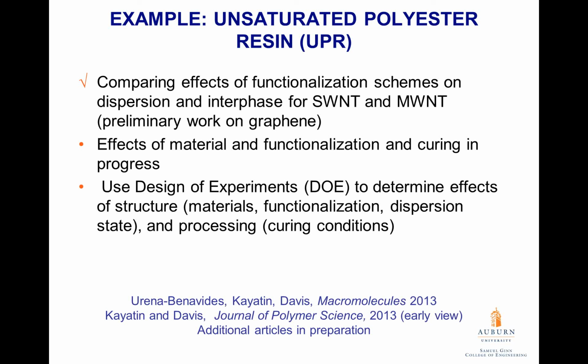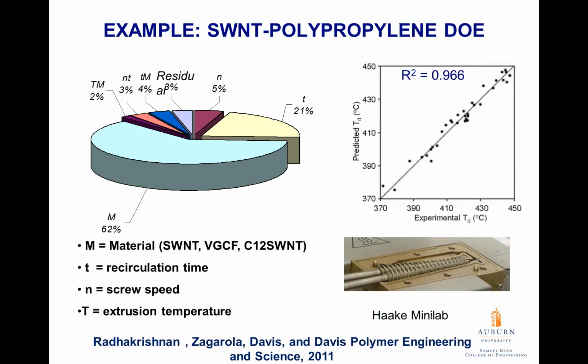Some of our previous work that we were able to take all the way through the process was on polypropylene. Polypropylene is a thermoplastic resin. It's one of the most commonly used resins out there. It's used in everything from carpet fiber to baby diapers to lunch boxes to cups and a huge host of other things. And what we did was we looked at how the materials we used, functionalized carbon nanotubes here with the C12 dodecyl group, vapor-grown carbon fiber, a much cheaper, much more imperfect and much larger analog, and plain single-wall carbon nanotubes, interacted with the recirculation time in this little baby extruder, screw speed, and extrusion temperature.